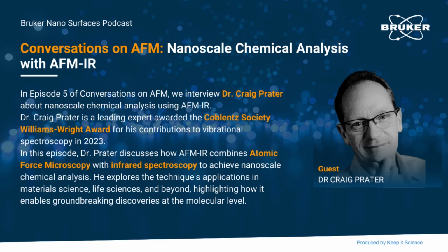And specifically how it works is there is typically a tunable infrared laser that is aimed at the region of the sample where the AFM tip is touching the sample. And if the tunable infrared laser is tuned to a frequency or a wavelength that corresponds to an infrared absorption band in the sample, then part of that laser light is absorbed as heat. And specifically what's going on is that if the vibration frequency of the light matches the vibration frequency of molecules in the sample, then part of that light goes into exciting the molecules, causes them to heat up.